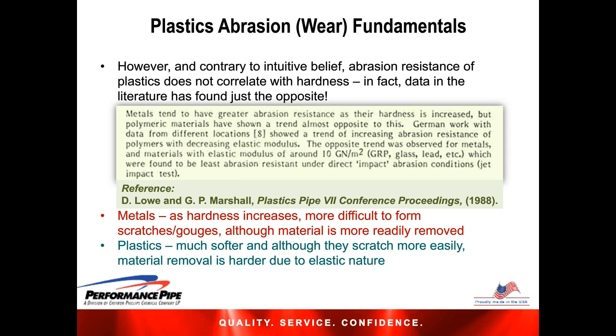I show a little snippet here that hopefully you all can see. It comes from this referenced article by Lowe and Marshall, and I'll take a quick minute just to read that. It says metals tend to have greater abrasion resistance as their hardness is increased, but polymeric materials have shown a trend almost opposite to this. German work with data from different locations showed a trend of increasing abrasion resistance of polymers with decreasing elastic modulus. The opposite trend was observed for metals and materials with elastic modulus of around 10 giganewton per meter square, which were found to be less abrasion resistant under direct impact abrasion conditions.